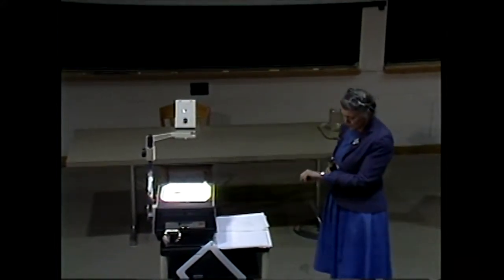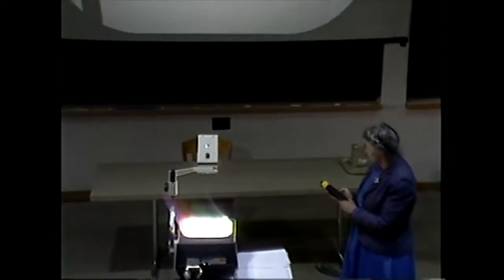Last time I talked about the use of ion implantation as a way to study regrowth in anisotropic materials. And I won't bore you with this again, except to say that in so doing, we used annealing as a method of recovery. So we put in the ions and we make this awful mess. We introduce a lot of damage, and then we anneal the sample and we anneal out the mess, and we try to regrow this system that we started with. And in so doing, we measure both the temperature dependence and the time dependence. The temperature dependence gives us the activation energy, and the time dependence gives us information on the kinetics.